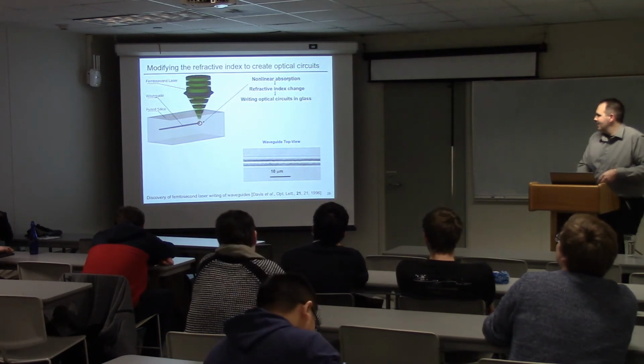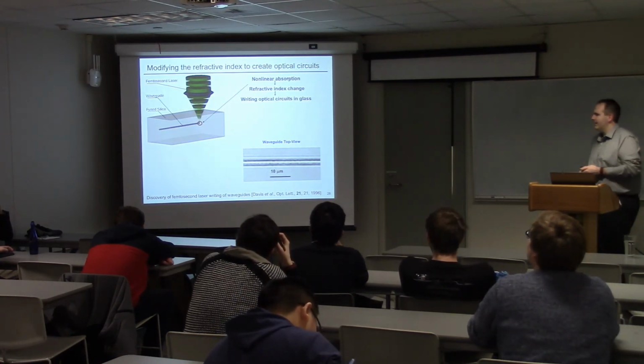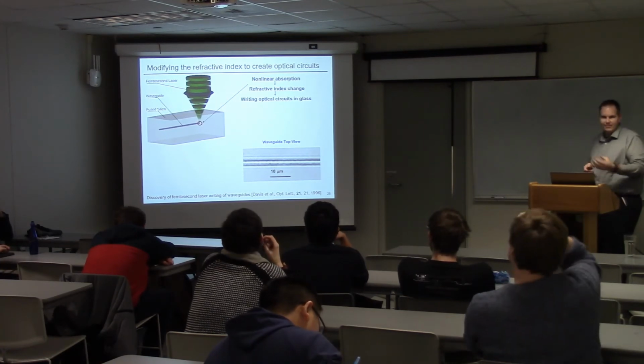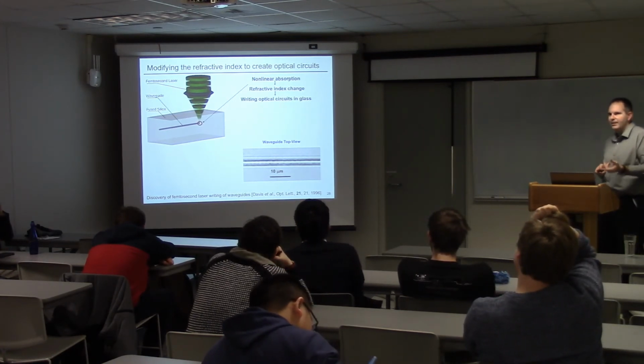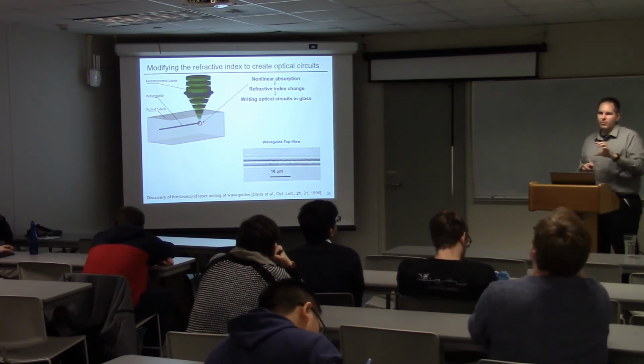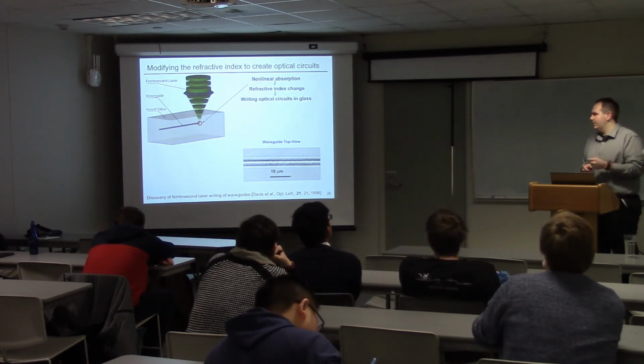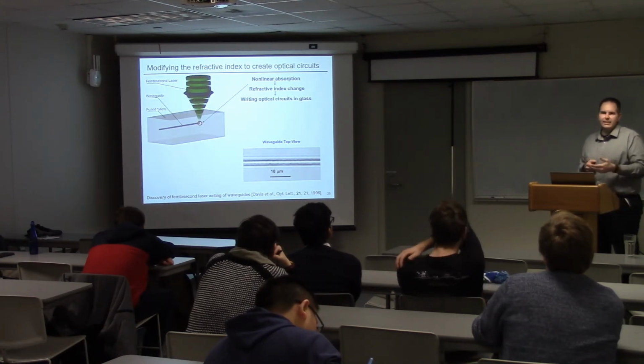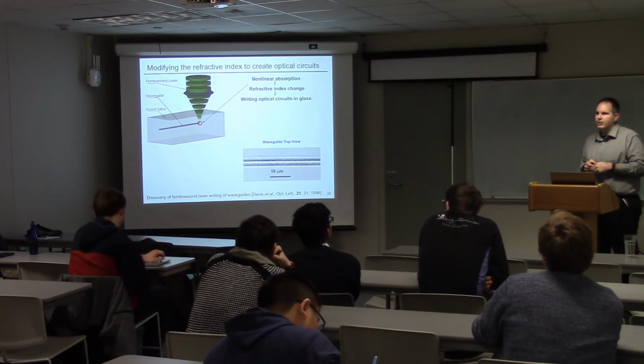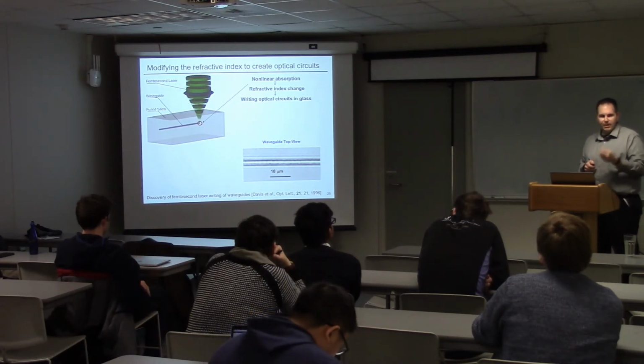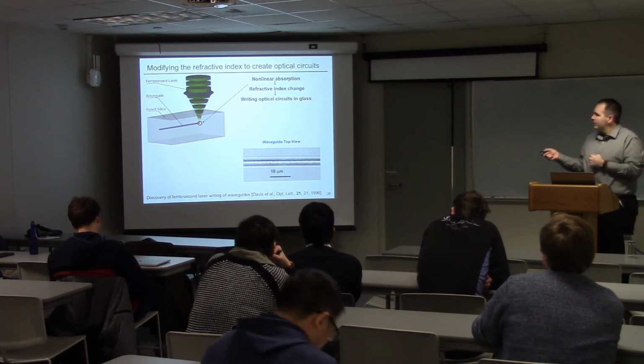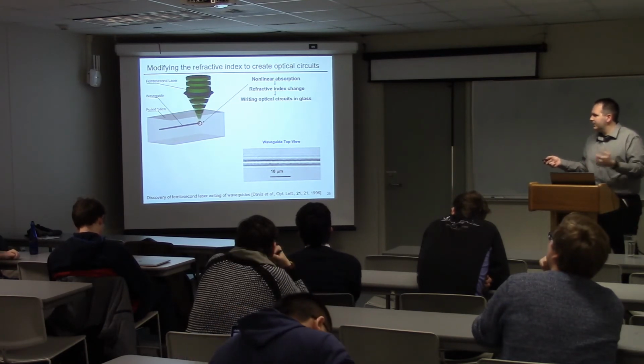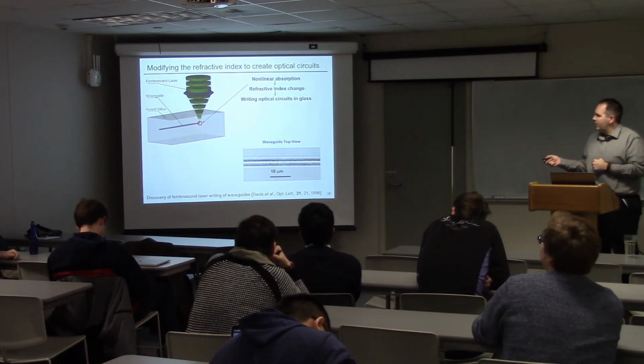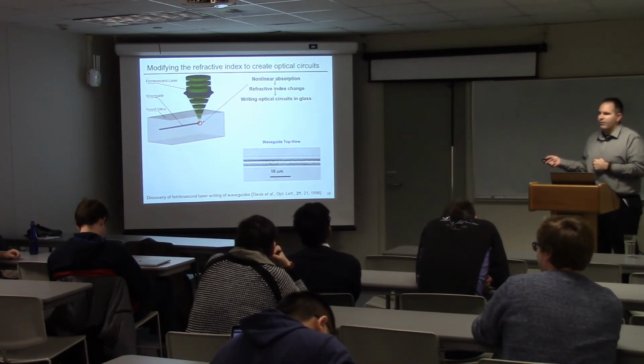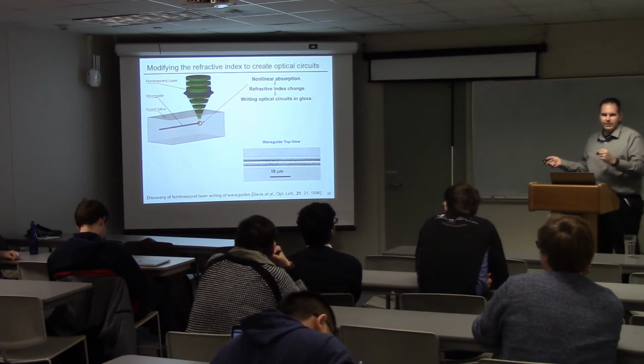All right, so we go now into the area of expertise from my doctorate, and that's refractive index change. If you recall back to the nonlinear equations, there's a term called chi3, which is responsible for giving you an intensity-dependent refractive index change. So you can change the refractive index of a transparent material by focusing really intense light into it. Showing here, this was a block of glass, in this case fused silica, and when you have these femtosecond laser pulses and you focus them very tightly, you can actually change the refractive index of the glass locally, only in that focal point where you've tightly focused the laser.